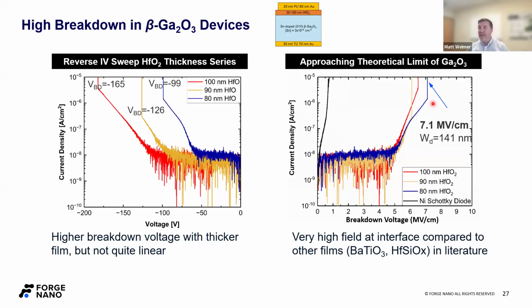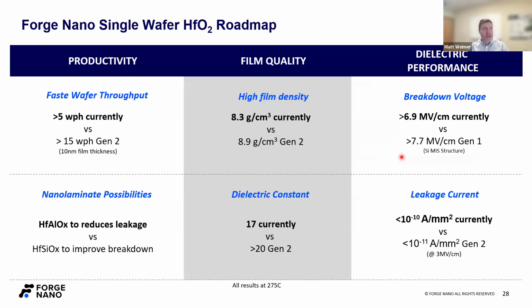We also know that when it comes to leakage, if we put a little bit of aluminum oxide in there, we can decrease our leakage even further. So I think there's a lot of potential here for not just ALD, but also the unique stuff that ALD can do, which is those nanolaminates. All right, so I'll put a little bit of information about our hafnium dioxide film here. We haven't fully released this one to production, so our wafers per hour currently is pretty slow, but we know how to increase that pretty easily. I've already talked about the laminate possibilities.